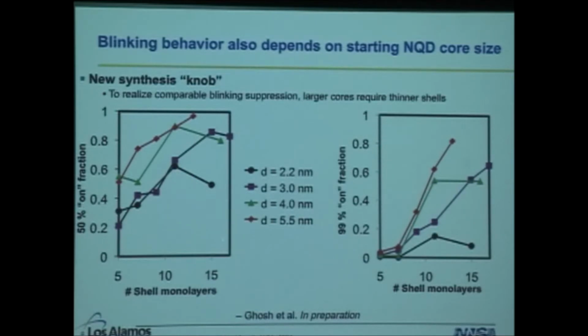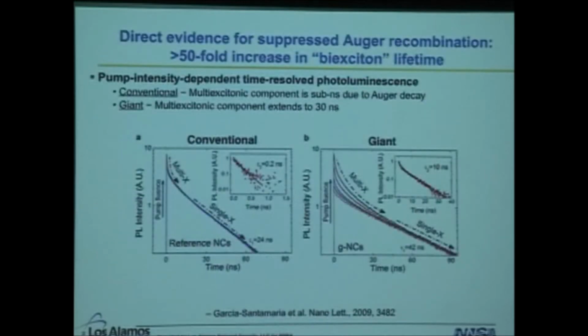It turns out that your starting core diameter actually makes a big difference. If we have a larger starting cadmium selenide core diameter, we need fewer shell monolayers to achieve equivalent blinking suppression as we do for smaller diameter cores. And it appears to be a volume effect. So effectively you start with a bigger core, you need fewer shells, you have the same volume as a small core and many shells. But it's not strictly correlated to that, so we're still trying to understand what's going on there.